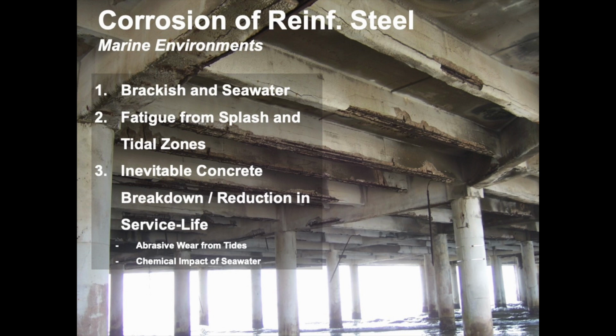Now we see this in marine environments because of the brackish seawater, the fatigue, the wetting and drying cycles, and the inevitable breakdown of concrete just to deal with these wetting and drying cycles, the volume changes, and of course the use of the concrete structure. And what this leads to is the concrete breaking down, the exposure of that reinforcing steel, and of course the harsh reality, the steel corrosion that we see in the picture included.